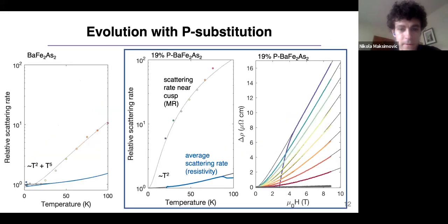So let me move on to the phosphorus substituted. Right, you make a good point. These plots are meant to be qualitative illustrations, and at least at reasonably low temperature, we can believe that the magnetoresistance is primarily controlled by the scattering rate. And as we phosphorus dope the system, this anisotropy becomes more and more pronounced. In 19% phosphorus substituted Barium-122, we see a very similar type of linear behavior in the magnetoresistance at high fields.